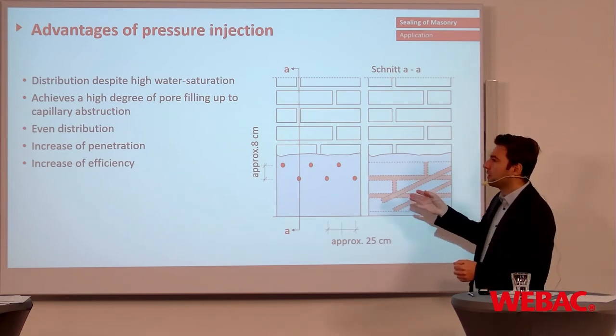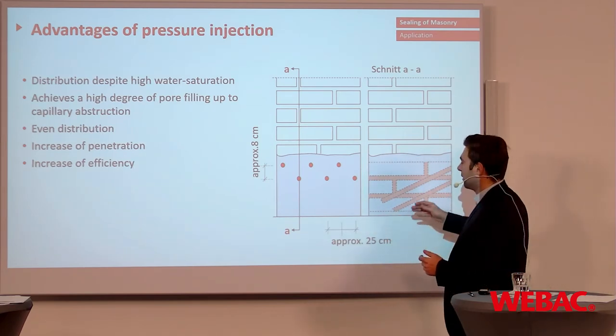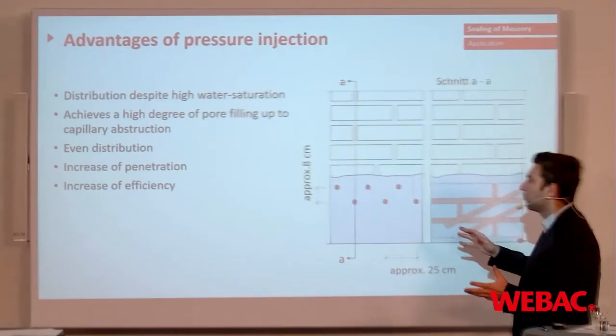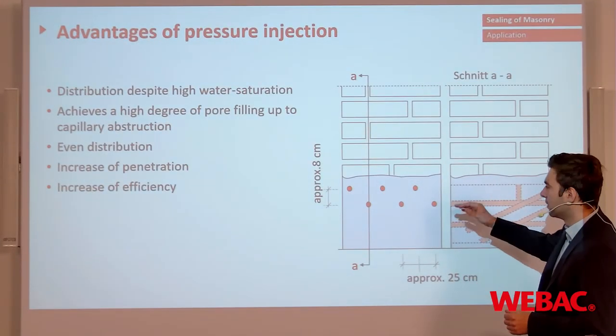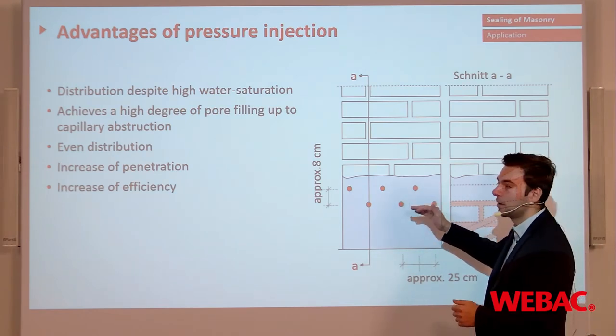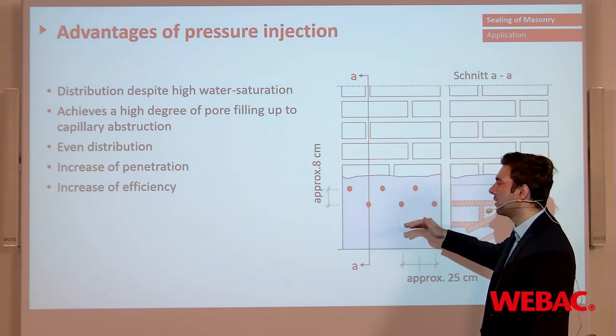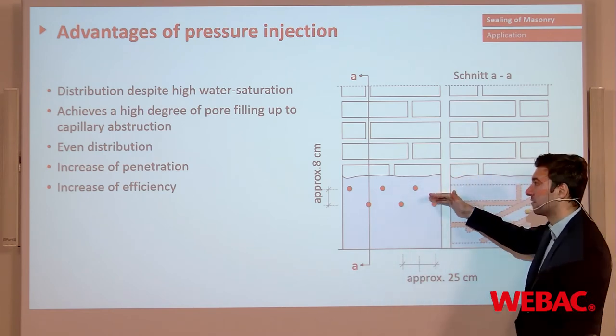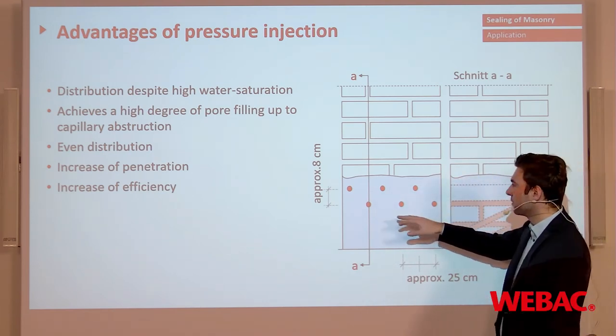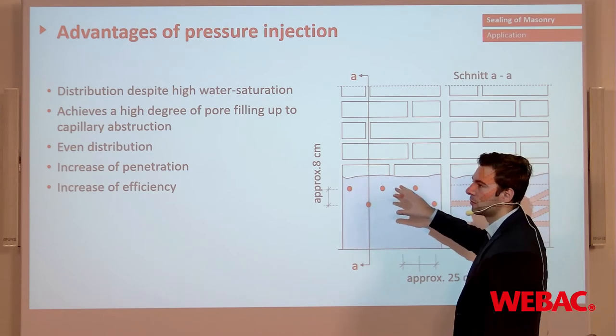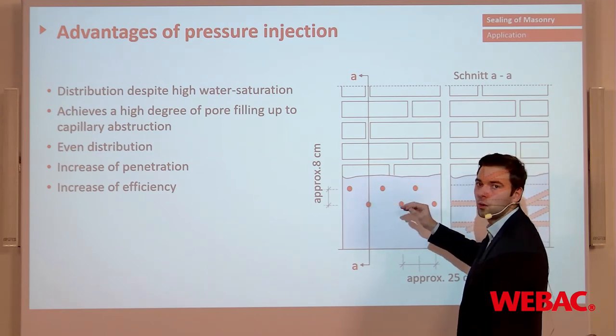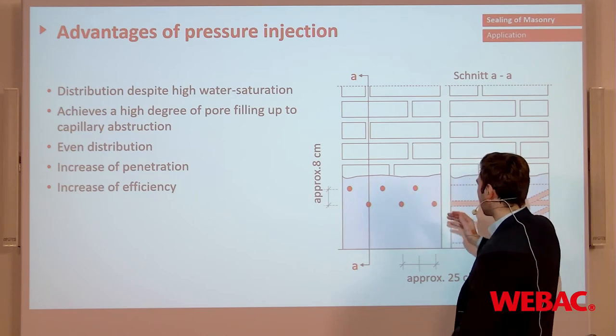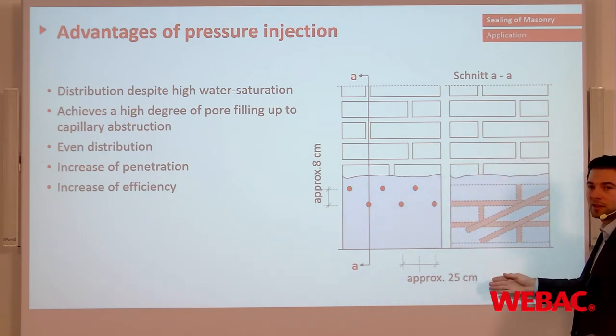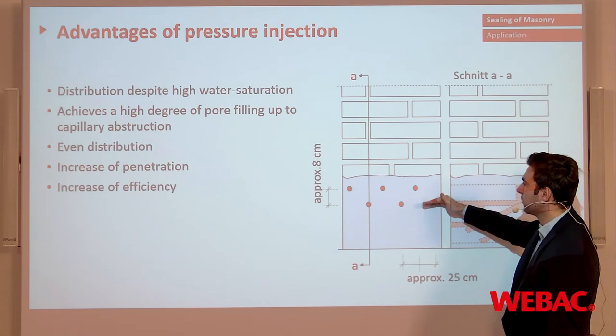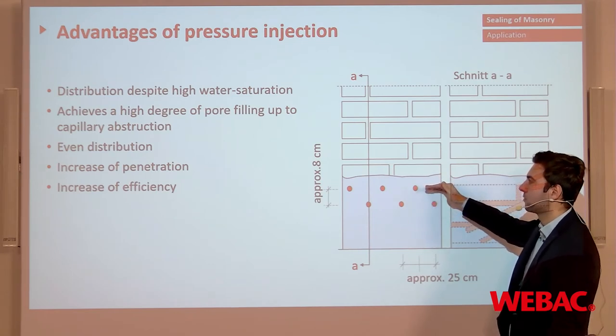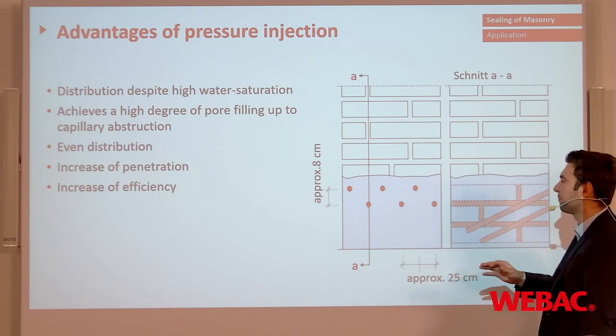From our experience and some German regulations, there is a rule of thumb more or less for how to drill. The distance between the packers depends on whether you are working in a one layer or two layer system. In this case it's a two layer system, and the distance between the packers should be 10 to 12 centimeters. If you are working with one layer, it's going to be approximately 25 centimeters. And the distance from one row to the second row has to be approximately 8 centimeters.